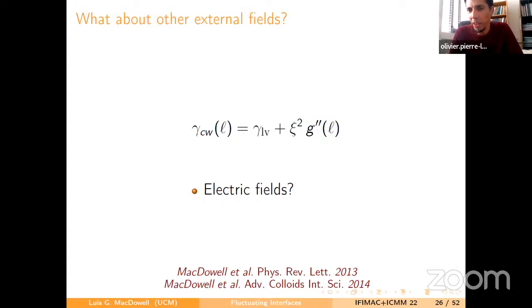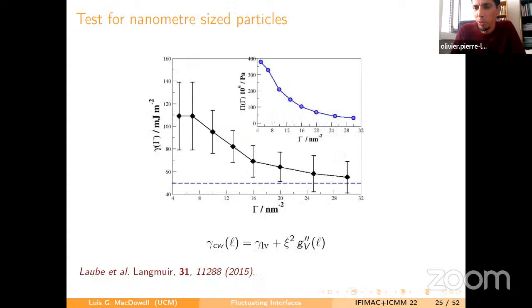the liquid becomes anisotropic. And so, as in the case of solids, in this case the prefactor of the Q-square term is not the surface tension, it is the stiffness, which is the surface tension plus the second derivative of the surface tension with respect to the orientation of the surface. So I did not see a distinction between surface tension and surface stiffness in your studies of liquid films influenced by the substrate. So could you comment on that?